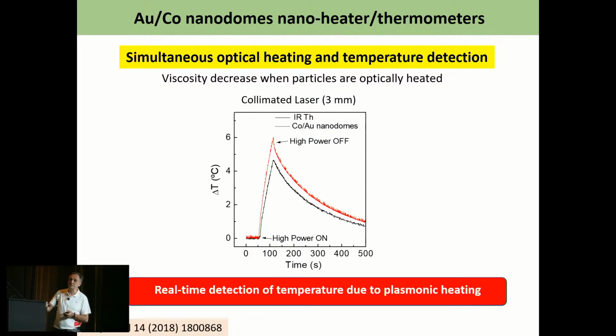The difference in temperature between the two systems is because the infrared thermometer is measuring the temperature at the surface rather than the temperature around the nanoparticles as the phase lag does. So that's why there is a small difference in temperature, because it takes some time for the heat generated at the nanoparticles to reach the surface, which is what is measured by the infrared thermometer.